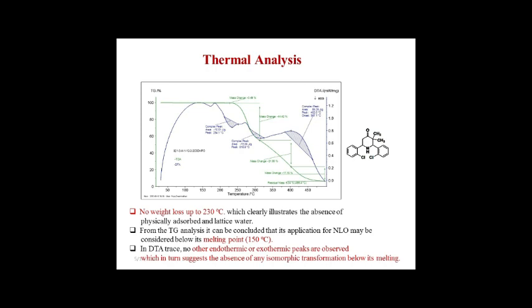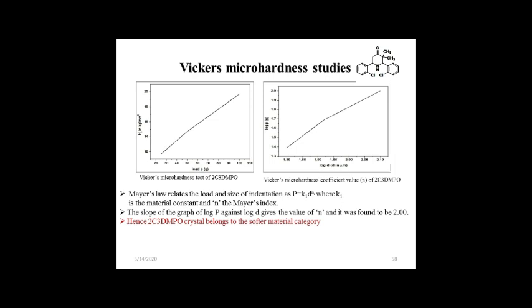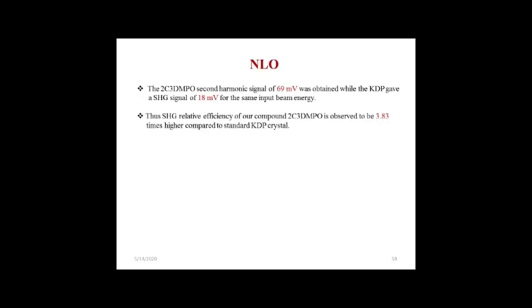Endothermic and exothermic peaks are observed, suggesting the absence of any isomorphic transformation below its melting point. There is no weight loss up to 230 degrees centigrade. The same for hardness, it is a soft category material. The NLO output is 69 millivolt and KDP gave 18 millivolt for the same input energy, so our compound is 3.83 times higher than KDP crystals.